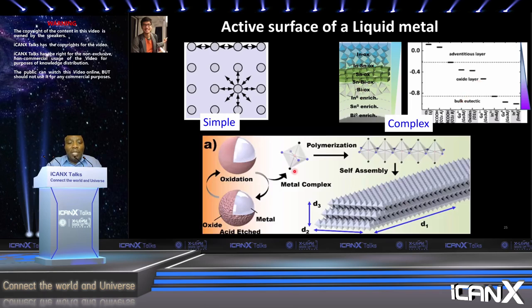Based on that hypothesis, we argue that if I start etching the surface of the metal, two things can happen. If I etch faster than the metal can be replenished, then I will start getting mixed metal ions coming into the solution. However, if I etch slowly enough that diffusion and replacement of the material from the bulk matches the surface, then I will get the same ion throughout, and therefore I can make